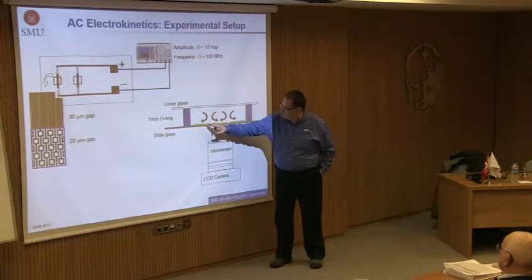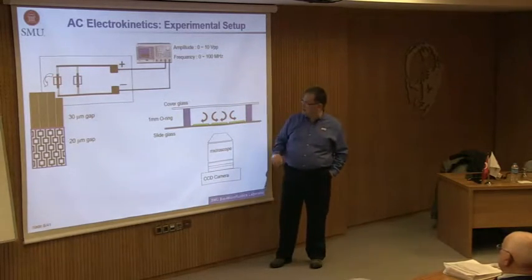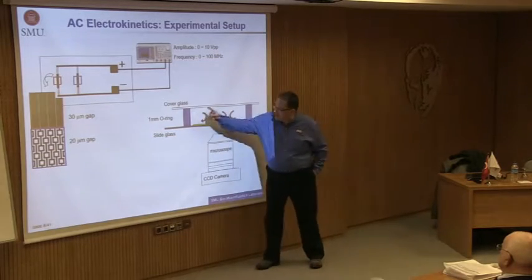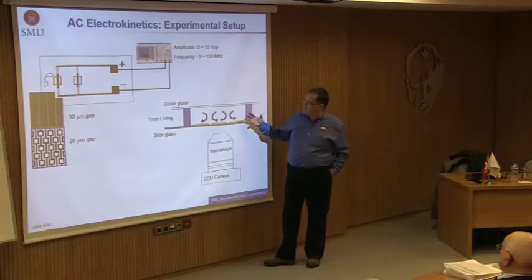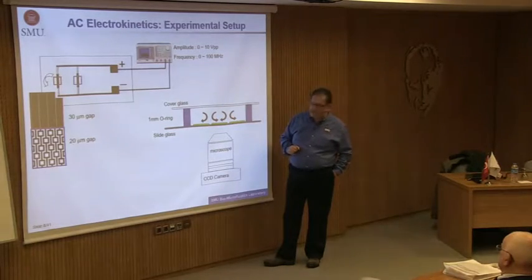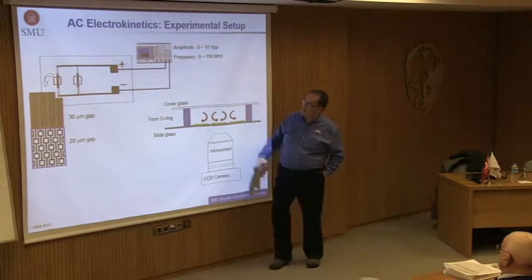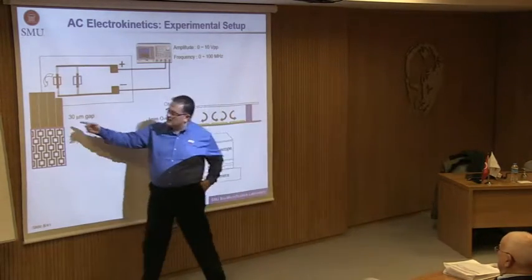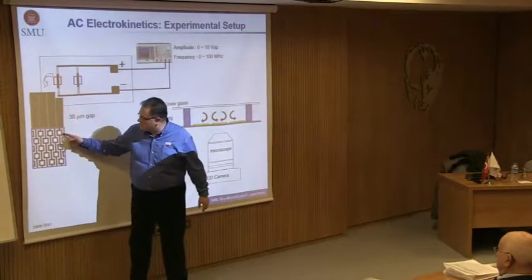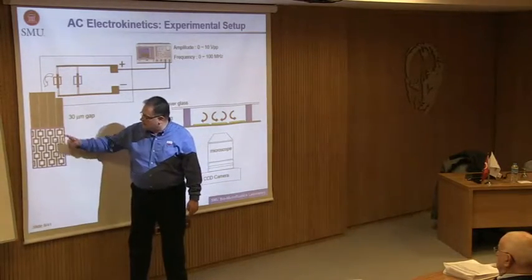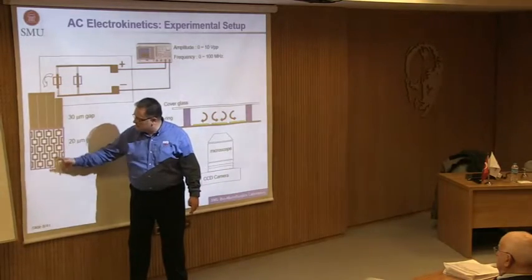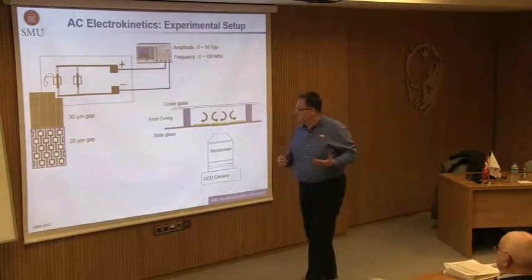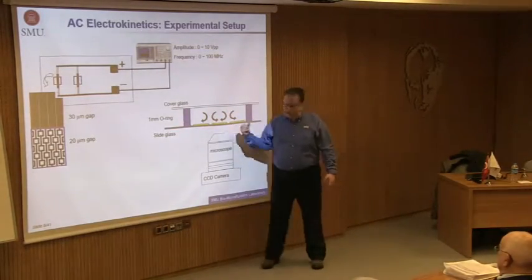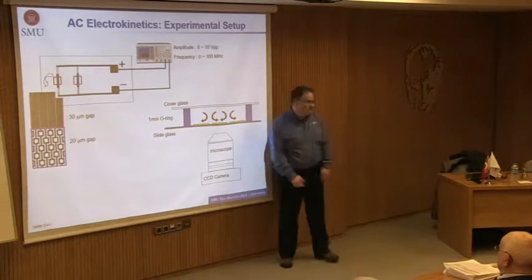So if you have electrodes, then you can apply different electric fields in there, and there are gaps and so on. You use an O-ring, and you put, for example, fluid with some colloidal particles or biological cells in it, and you basically change the applied electric frequency and the voltage. You can have very simple electrodes like interdigitated geometry, or you can have things that have squares and so on, and at a given time, say this is positive, that's negative, and so on, and it's an AC field. So what we do is that we look from the bottom, and we observe the response of colloidal particles to the AC electric field.